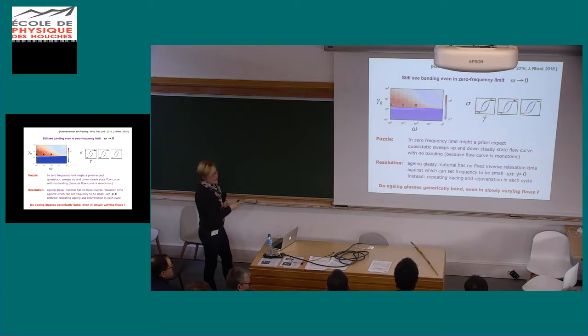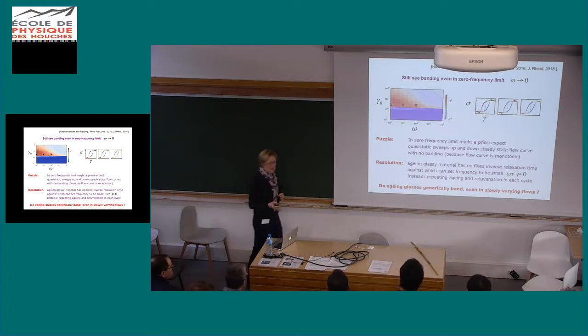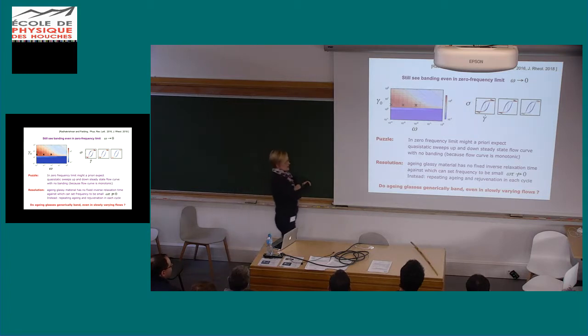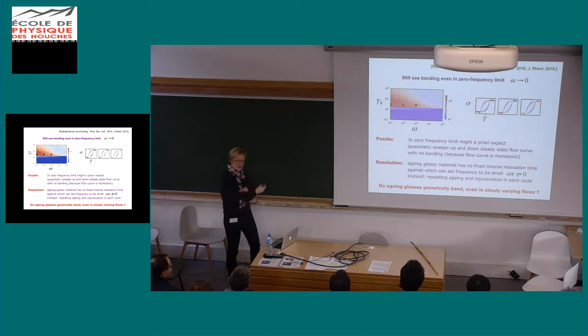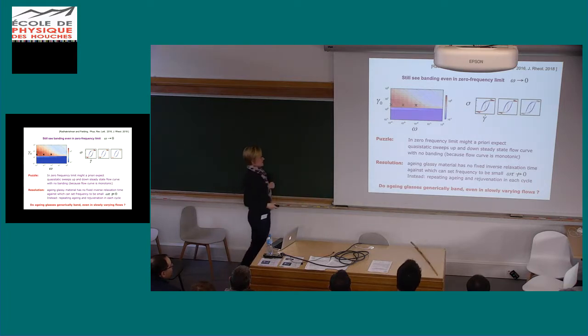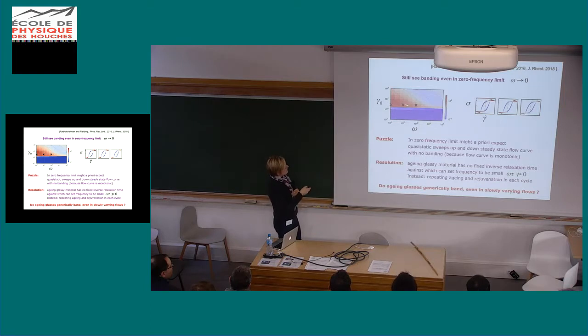There's no evidence for that, and indeed there shouldn't be, I only realised later, because my intuition stemmed from thinking about ergodic polymeric materials where there's a finite relaxation time, which you can always take the frequency to be low compared to. In these aging glassy systems, there is no fixed relaxation timescale. The relaxation timescale is actually then somehow set by the frequency, so you can never reach a state where you're shearing slowly compared to the aging time. And so that means that shear bands persist in this oscillatory flow even in the limit of effectively zero frequency.